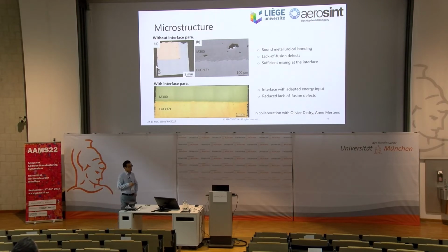What we found out is that if we stack the M300 on the copper alloy, of course, in the first few layers we have lack of fusion defects, simply because our parameters for the bulk were developed when the material is on the steel build plate.